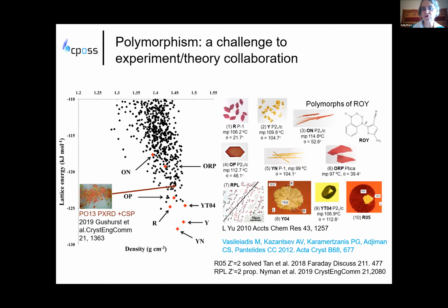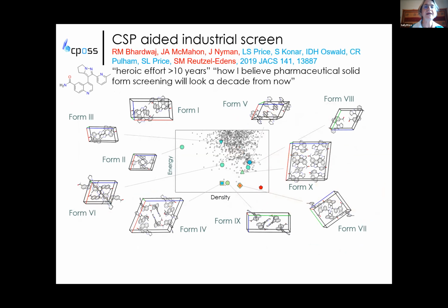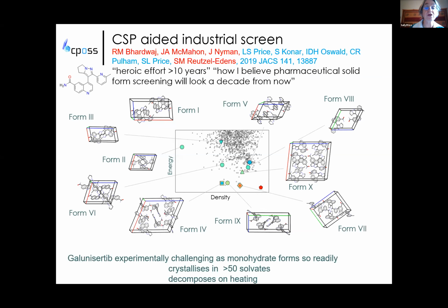So here we've got a lot of polymorphs. They grew with time. This is another example of a polymorph screening, which was a long period done systematically with industry. It took them a long time, and we've eventually got the structures of 10 different polymorphs here shown on the crystal structure prediction diagram. This was difficult because this drug molecule readily crystallizes as a monohydrate, and they were really interested to see whether there was an unhydrated form that was competitive with this. In fact, it crystallizes with virtually every solvent and decomposes on heating.